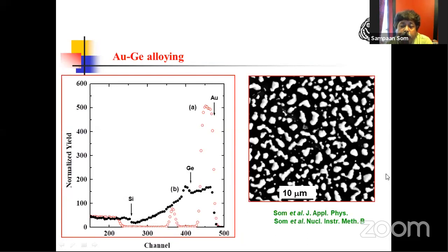The films have got dewetted. This is known as spinodal dewetting. They have got dewetted, and several bright islands on the black background are created. When we do RBS measurements from this particular kind of sample, whose representative image is right on your screen, with the black scale bar of 10 micrometer, we get to see the corresponding RBS spectrum like this. You can see it marked as B.